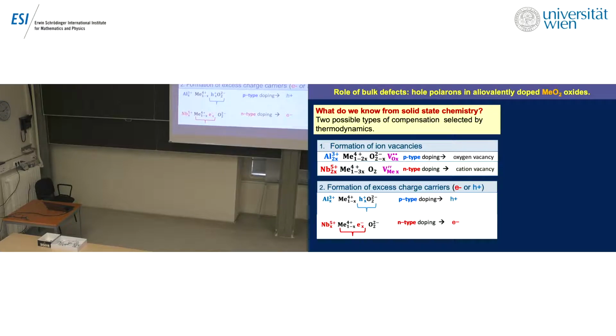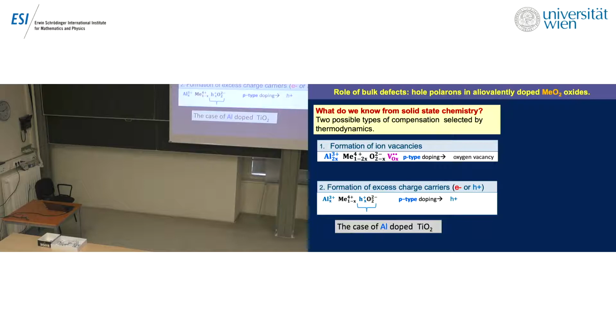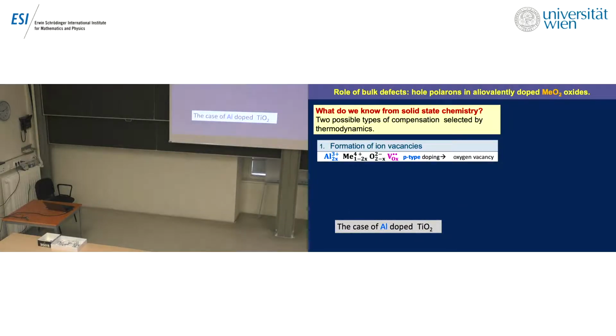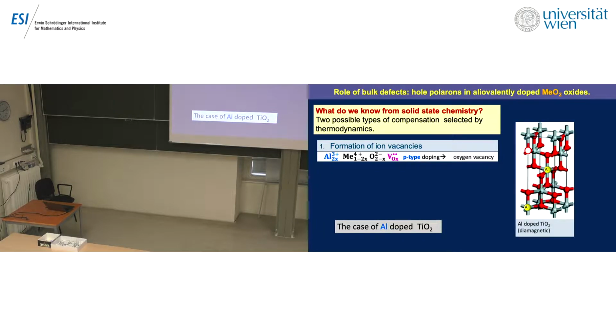And the response of the system is not granted. There are two possible responses that are determined by thermodynamics, in the sense that you can have the formation of vacancies. Here is an oxygen vacancy when you have aluminium, or a metal, a cation vacancy in the case of niobium. But you can also have directly the stabilization of a hole in the first case, or an extra electron in the second one. What I want to discuss today, initially, is the case of aluminium, okay, and so we skip the niobium, and the case of aluminium-doped titanium dioxide is such that the solution that the system prefers is this one. So we have aluminium in the system, in titanium dioxide, with some oxygen vacancy.